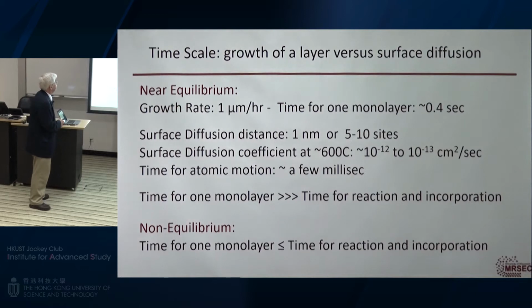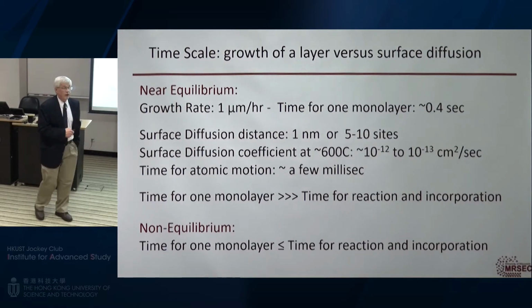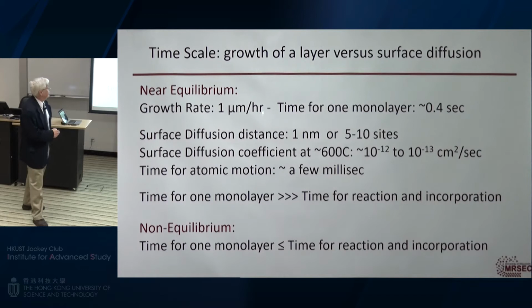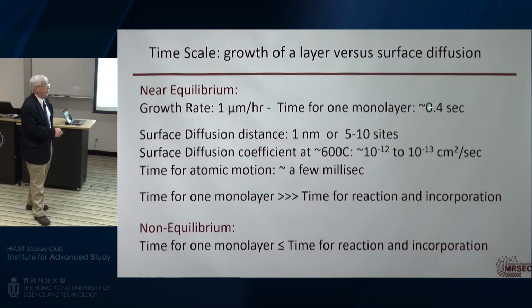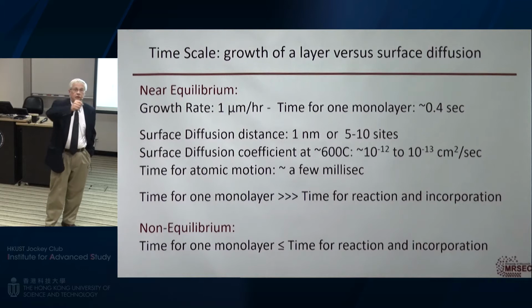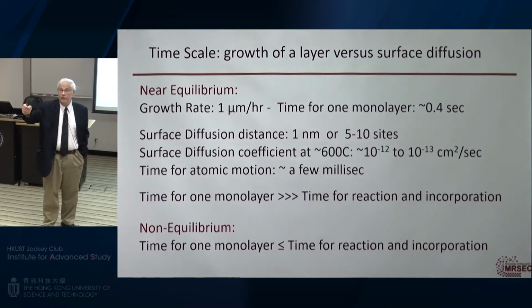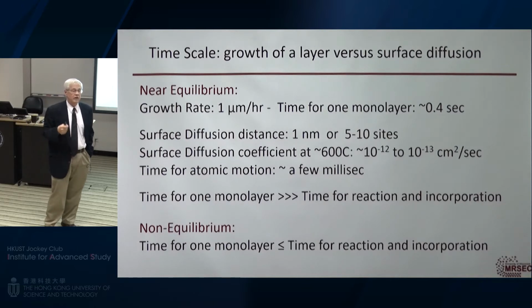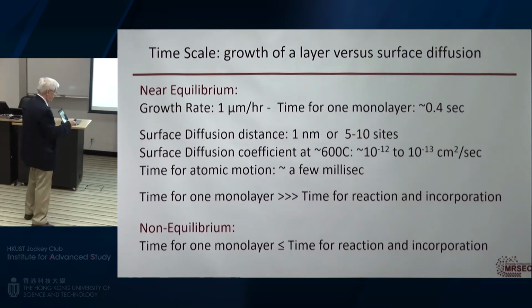If you're near equilibrium, so let's say a typical epitaxial growth rate is about a micron an hour, which means the time to grow one monolayer is about a half a second. Right, so this is in a CVD system. If I look at how atoms diffuse on the surface, and let's say I have an atom come down, for it to find the right spot, it's going to move around on the surface and then find a location that has the lowest energy. Let's say it has to move on the order of a nanometer to do that. That's 5 to 10 atomic sites, depending on the size of the crystal.